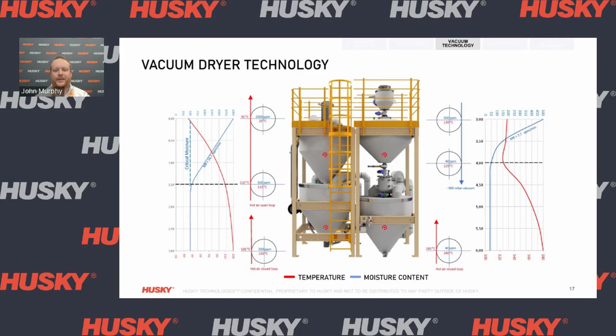And then when we look at stage 4, we see no change in humidity because we've already reduced to below 40 ppm, but we do see an increase in temperature up to around 180 degrees in this example, making it the ideal case for the injection molding machine.